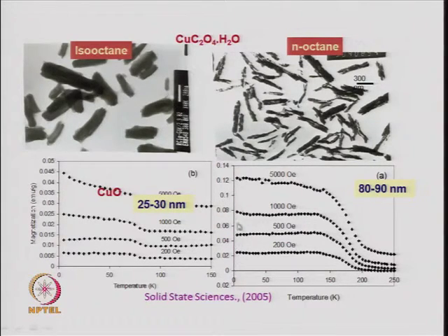So, this axis is magnetization. There is an increase in the magnetization at around 200-210 Kelvin. So, both these particles show some kind of a weak ferromagnetism, because whatever was the magnetization earlier, now the magnetization is increasing. So, this sudden increase in magnetization is actually ferromagnetism, if it is very sharp. That is most commonly the reason why the magnetization should increase. Since the increase is not as sharp as a normal ferromagnet, hence we sometimes call this weak ferromagnetism.